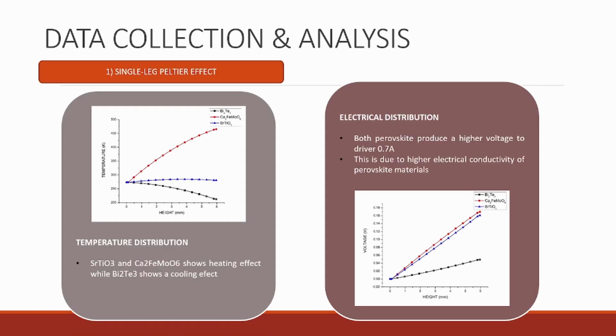Data collection and analysis for the single leg Peltier effect. First is temperature distribution. As you can see, strontium titanate and calcium iron molybdate show a heating effect, while the bismuth telluride shows a cooling effect. For the electrical distribution, both perovskites produce a higher voltage to drive 0.7 ampere. This is due to the higher electrical conductivity of the perovskite material.